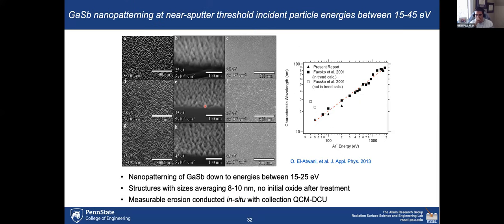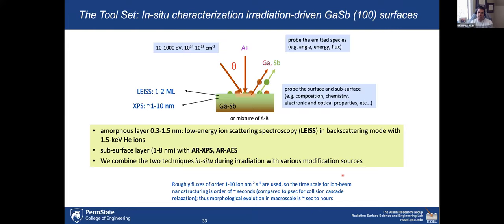So we did another study where we carried the energy of the ions from a sputtering dominated regime down to sub-sputtering threshold regimes. This was the study of Osman El-Atwani and his PhD that demonstrated that you don't need to invoke this mechanism of etching or sputtering, that there's some other mechanism at play, since we're also able to get patterns on these gallium antimonide surfaces, even down to 25 electron volts. So the question is, what was driving these mechanisms?